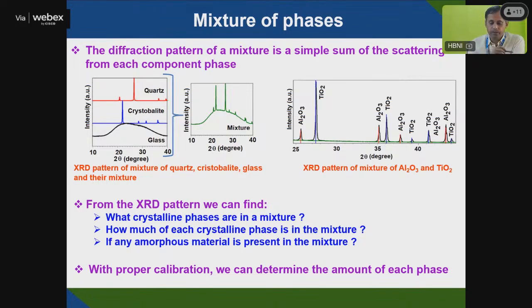For example, in a mixture of phases, you can see this is quartz, this is cristobalite, and this is glass. Silica exists in these three forms: amorphous, cristobalite and quartz. Individually, they look like this. You get an amorphous phase in the case of glass, and crystalline phases in the other two. But if you get a mixture, you can see the amorphous glass is there and then a sharp peak is there. So this type of identification can be done using X-ray diffraction.